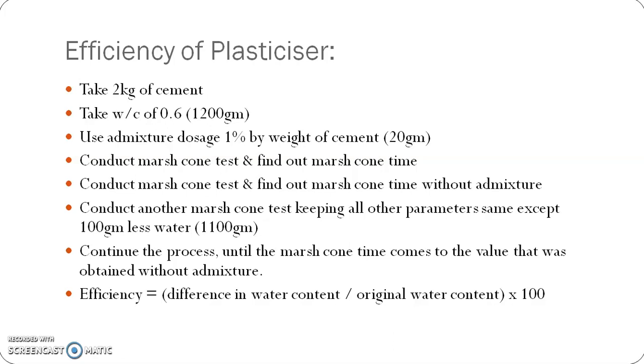Conduct another Marsh cone test keeping all the parameters the same except 100 gram less water. So first time we are using 1200 grams of water, and next you are reducing by 100 grams. Continue the process until the Marsh cone time comes to the value that was obtained without admixture. Then compare the value without admixture and this with admixture. At that point you stop the test. You can find the efficiency as the difference in the water content divided by the original water content, into 100. This will give you the efficiency of the plasticizer.